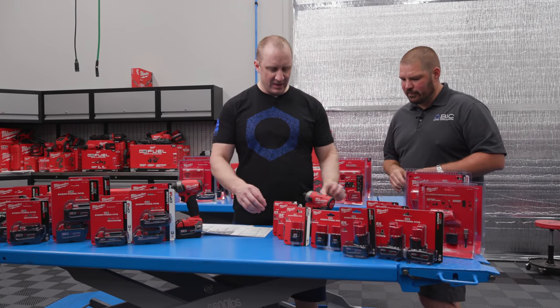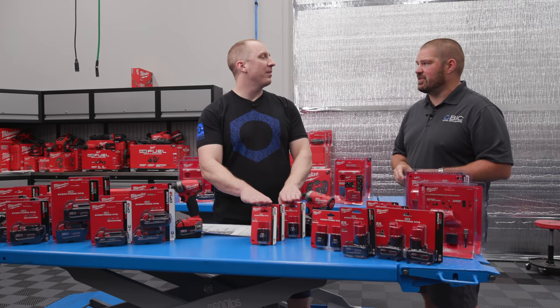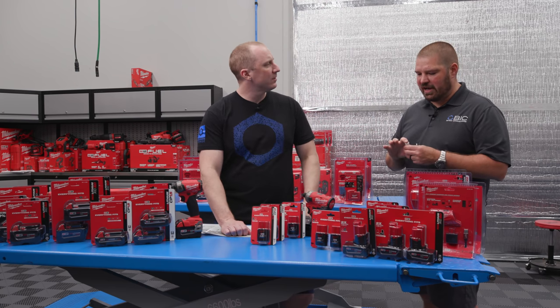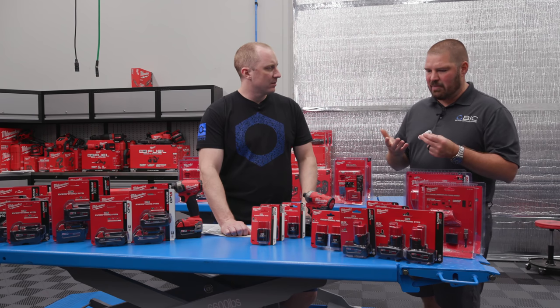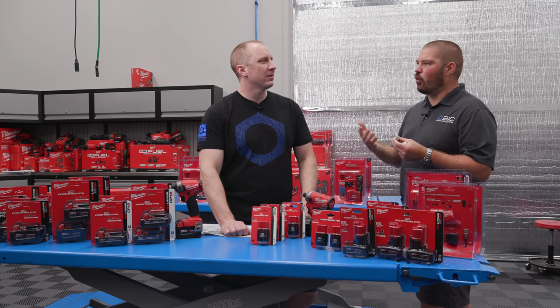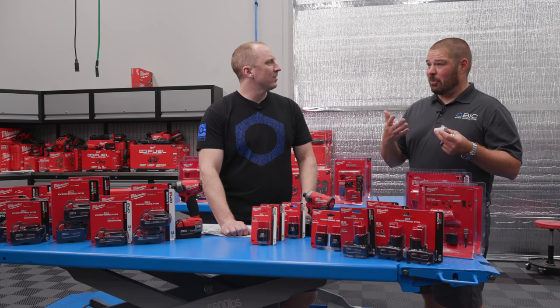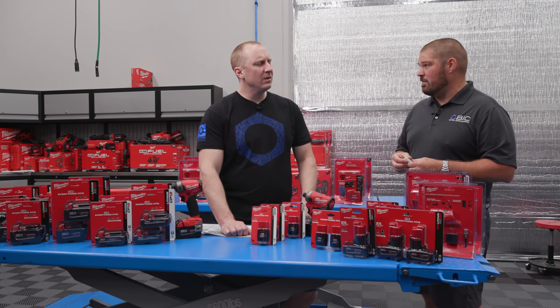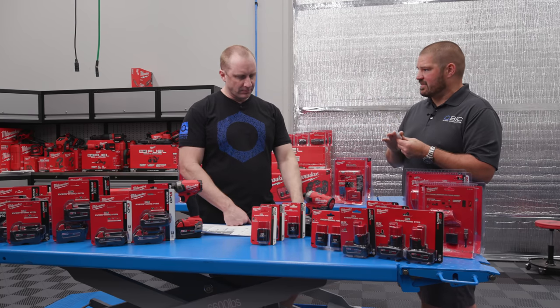So these are likely all wired the same internally — exactly the same in that series — but they contain a different 18650 cell. If you look at 18650s by capacity, general ones might be 1,400–1,500 milliamp hours (1.4 Ah), all the way up to emerging tech today at 4.2–4.3 Ah in the same physical outer package.